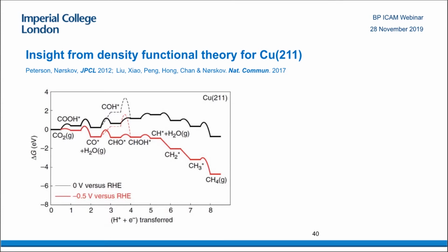To try and understand why CO2 reduction is so inefficient, even on copper, which is the best material, here we've got the DFT calculations from the group of Jens Nørskov and Karen Chan. Here's the free energy diagram showing barriers. This is at 0 volts, so essentially no bias, and then this is at minus 0.5 volts. You need to drive the reaction quite far to decrease these barriers considerably enough to get a reasonable or measurable current density. What you can see is there's one step in particular which is really, really uphill.